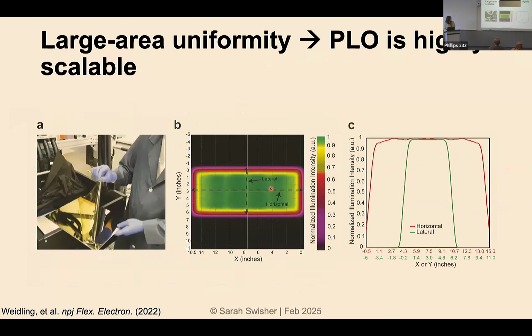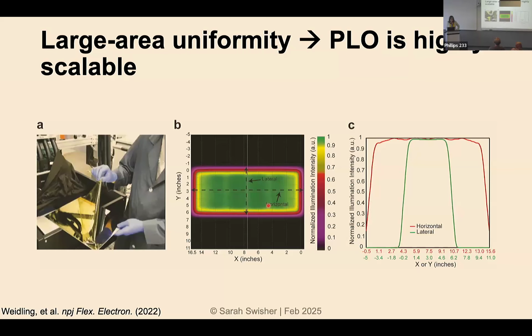The other thing that I want to point out about this method is that we get the ability to do very large area processing. So the tool that we have in my lab is a research tool, so it has a relatively small processing area. But what we can do with the production grade tools is they have multiple lamps lined up together, and they've designed the optics and the interior of the device so that you still get this very, very nice uniform illumination here. This is the illumination intensity, and you can see that the illumination intensity is very flat across this whole region, even though this is actually multiple lamps lined up to increase your processing area so that you can get even higher throughput in a commercial process.